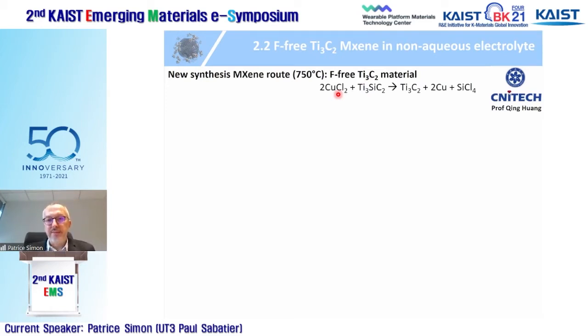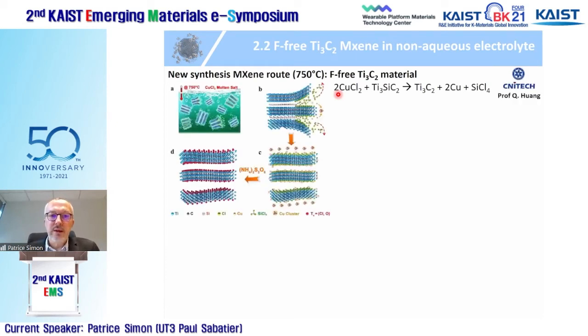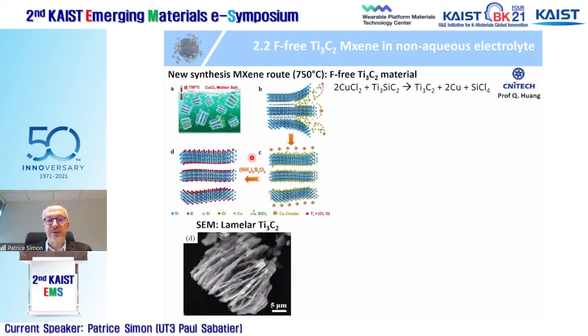And then what happens during this reaction is that copper 2+ ions from this Lewis acid are going to be reduced and oxidize the A element, which is here the silicon from a MAX Ti3SiC2 phase. So you reduce copper 2+ into copper, you oxidize silicon into silicon 4+, and then you end up with the MXene phase. And this is what is written here. However, you can see that you reduce copper onto the surface of the MXene here. And then what you need is to oxidize this copper present by washing with ammonium persulfate.